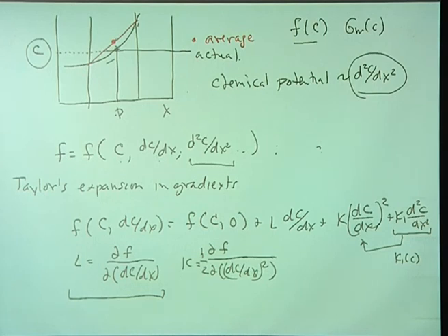And this has an interesting story, by the way. If you think about it, you have to have long-range interactions, or interactions over a distance p that's on the scale of multiple lattice parameters, for this model to work.